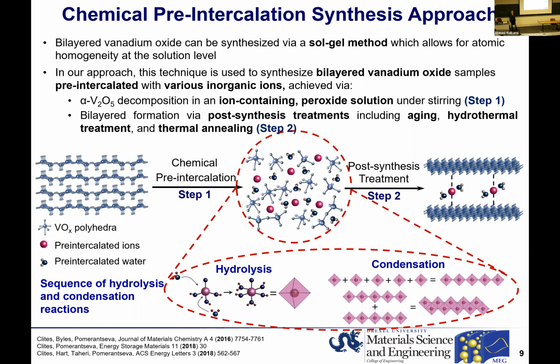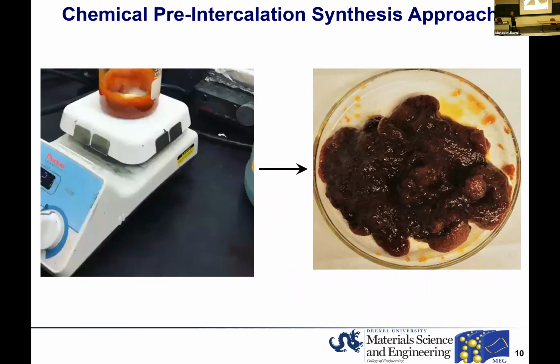So our idea was very simple. Why don't we do the same, but in the presence of specific cations, like lithium cations, during this solution stage of the synthesis? So these red spheres in the schematic essentially indicate these different types of cations that are being incorporated into the solution during the synthesis process. Cations are positively charged, and these vanadium oxide bilayers are negatively charged. So through simple electrostatic interactions, the cations get trapped in the interlayer region of the growing bilayered vanadium oxide. And that was the idea which worked really well.